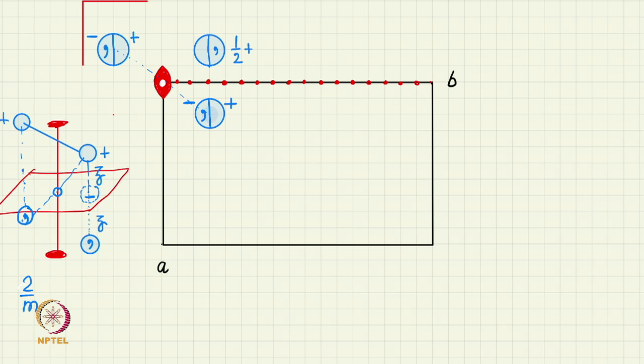Similarly, the minus z will also reflect. On reflection the height does not change, it remains at minus z, but then when we translate by c/2, that is half, it will become half minus z, which will be represented simply by writing half minus. So, I now have 6 symmetry equivalent positions.